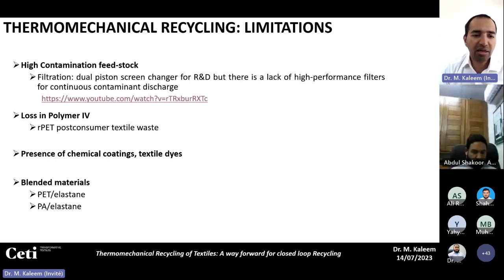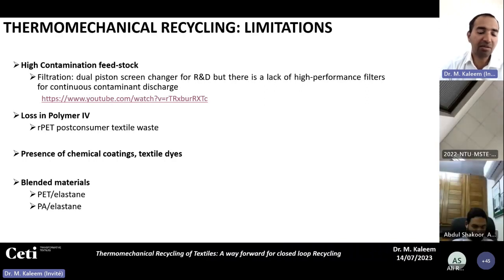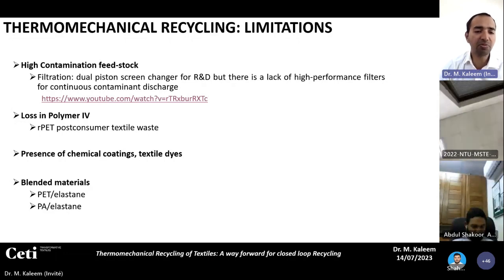Yeah. And then if your feedstock contains a blend of two materials, which is common these days, like a blend of polyester and elastane, or polyamide and elastane based material for apparel textile. These two materials, for example polyester and elastane, process at different temperatures. So if you put them in the thermomechanical process, maybe the elastane can burn and become an impurity in your recycled material. So you have to be careful, and you must know the certain percentage of elastane. Because we are limited, you cannot process a high percentage of elastane with polyester fabrics, for example. So you have to be very careful when you process your material in the thermomechanical recycling process.